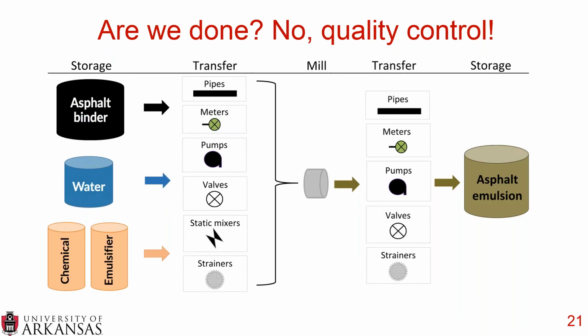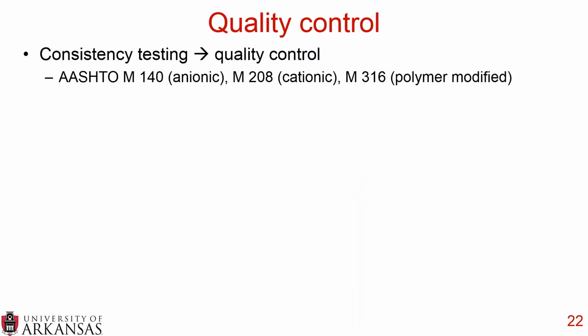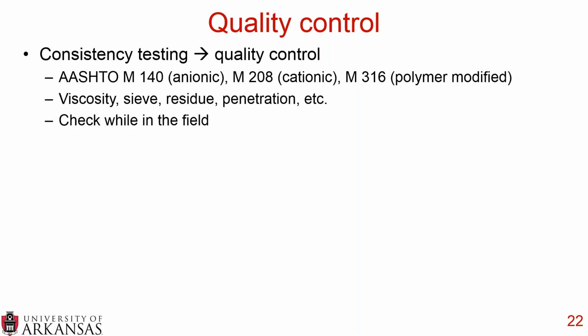You may ask, are we done? And the answer is no, because I do want to just mention quality control briefly. Quality control is so important. You have consistency testing, and this is found in AASHTO M140, M208, and M316. That covers anionic, cationic, and polymer modified asphalt emulsions. This is a very important part of quality control. This is where you measure things like viscosity, sieve, residue, penetration, and these are materials or properties that you can check while you're in the field. So if you're agencies, these are the type of things you want to track to make sure that you're getting the product that you ordered.